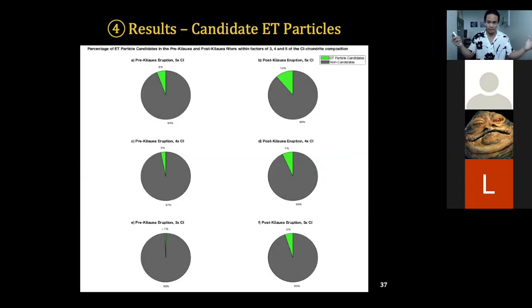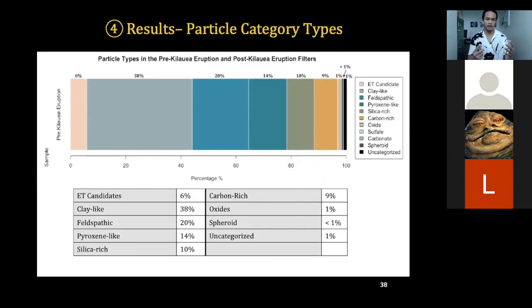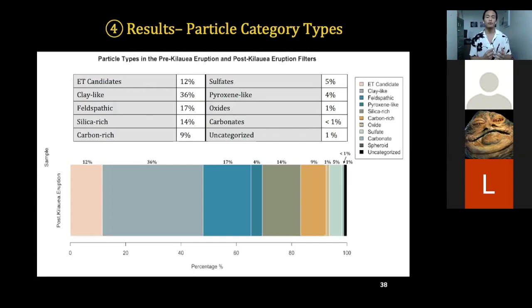After I've divided them into two categories, we further analyzed the non-candidates, or the background particles, which I will talk about here. Starting with the pre-Kilauea eruption filter, again with a factor of 5, we got 6% ET candidates, 38% clay-like, 20% feldspathic, 14% pyroxene-like, 10% silica-rich, 9% carbon, and then 1% for oxides, spheroids, and uncategorized particles. Moving on to the post-Kilauea eruption filter, we were able to find 12% ET candidates, 36% clay-like, 17% feldspathic, 14% silica-rich, 9% carbon, 5% sulfates, 4% pyroxene-like, and then 1% for oxides, carbonates, and uncategorized categories.